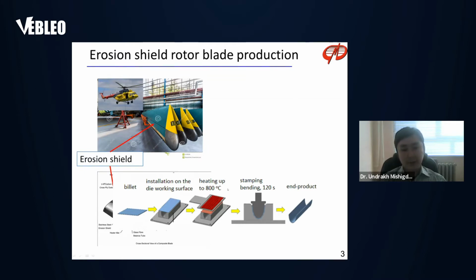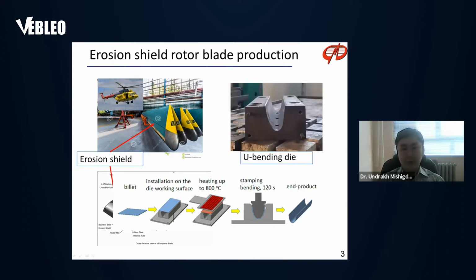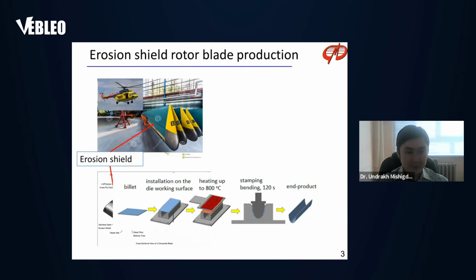So, the billet before punching is heated up to a temperature of around 800 degrees Celsius. Then the desirable profile can be obtained between the die and punch. This U-bending die is made of steel H21, and this is actually our motivation for the research.